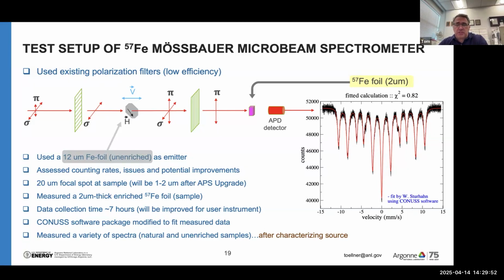What it does show, though, is the stability is quite excellent because the fitting was straightaway. There was no additional broadening one had to introduce. This was something I was concerned about because the emitter and the sample are on different tables, and so tens of micrometer per second vibration velocities can affect the data. This setup just had a 20 micron spot size, but this will be improved to 1 micron. And the Conuss software has been modified by Wolfgang Sturhahn to allow an arbitrary energy source spectrum so that one can fit. And the 4-line spectrum is available to that package as well.